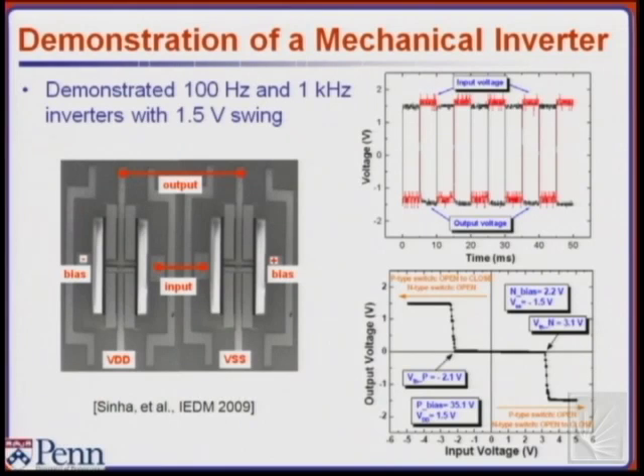So here's the response of a similar device. Here is an inverter that is switched with 1.5 volts on and off, a mechanical inverter. And here, the transfer function of that mechanical inverter, and if you are a logic guy, you realize immediately there's a problem here because this is too big, right? Basically it becomes a tri-state kind of logic device. Well, this is at a VT of 3 volts, right? We have VTs of 1 volt, and if you can reliably make those VTs of 20 millivolts, this region will substantially disappear. It really makes it a two-state logic like you have in CMOS, but now with a threshold voltage of hopefully 20 or 30 millivolts, not anymore a 1 volt or 0.7 or 0.5 volt threshold voltage.